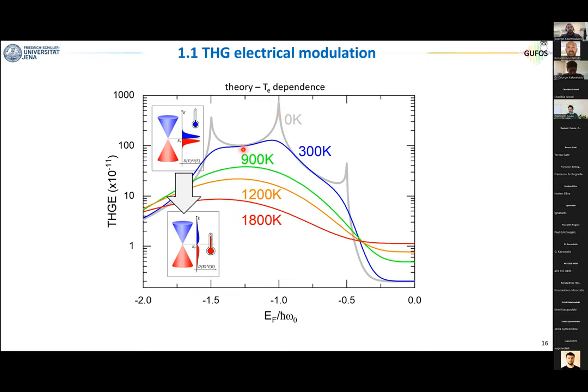So if you now extend the theory to certain values of the electronic temperature, you get these other colors of the curves. And you can easily understand what is happening by considering that as you increase the electronic temperature, you broaden the Fermi-Dirac distribution. And this broadening of the Fermi-Dirac distribution broadens these very sharp peaks. They merge into a sort of featureless modulation of the high harmonics.